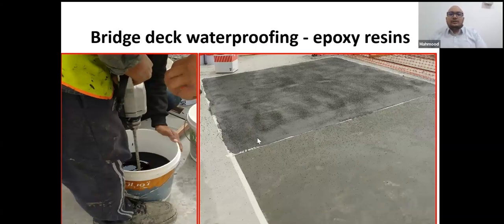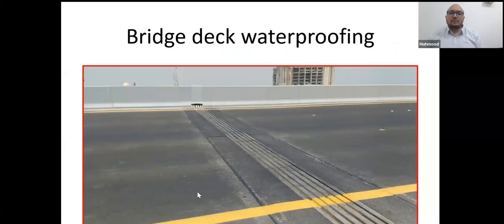They're applying epoxy-based bridge deck waterproofing. They're mixing the epoxy base and filler. They apply the primer. After applying the epoxy, they'll sprinkle the aggregate over it. Then the asphalt can be laid. Even without asphalt, you can use.